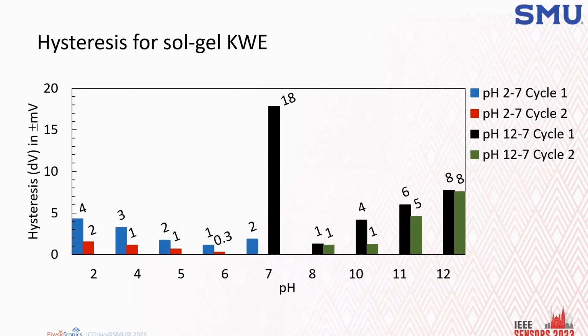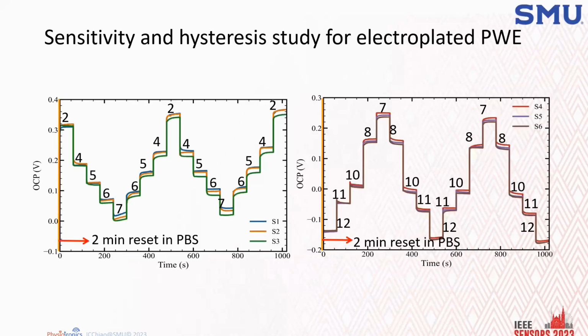So this is for sol-gel. For electroplated, because electroplated devices are uniform, across all 6 devices the performance is roughly the same. Again, we do cycle 1 from 2 to 7, 7 to 2, that's the first cycle. 2 to 7, 7 to 2, that's the second cycle. And for alkaline it is 12 to 7, 7 to 12. And we do find that the performance is repeatable after the reset.